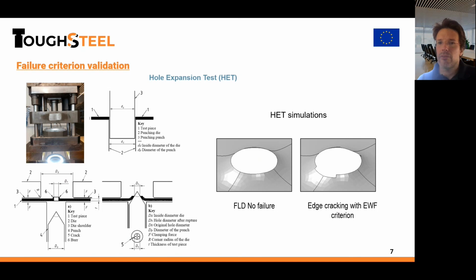The next one, please. We can also use the model to analyze the hole expansion operation. But we have the limitation of the mesh size because, as I explained, we use a 1 millimeter element length, and in some cases this 1 millimeter length is too big to mesh small holes. In this case, for example, we show a hole of 10 millimeters of diameter, and again we can see how the model shows the failure. And when we use only the FLD, we don't have failure in the hole.